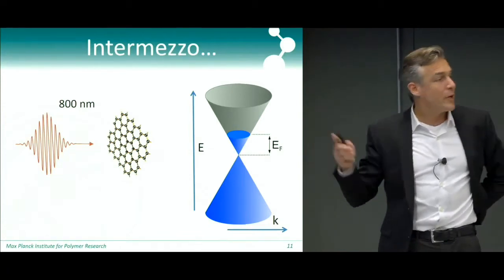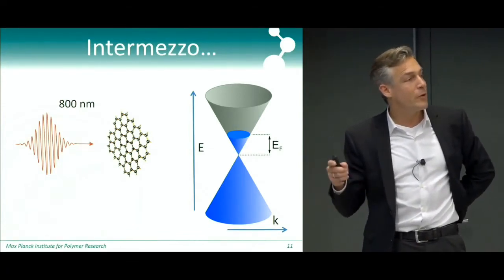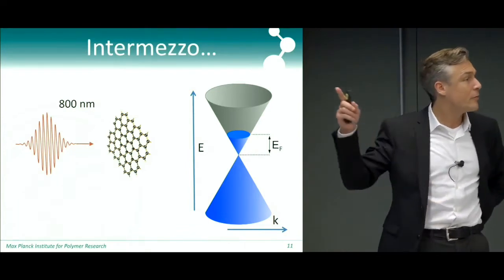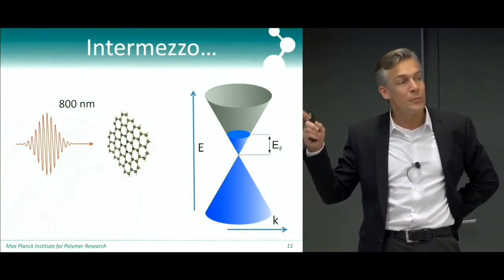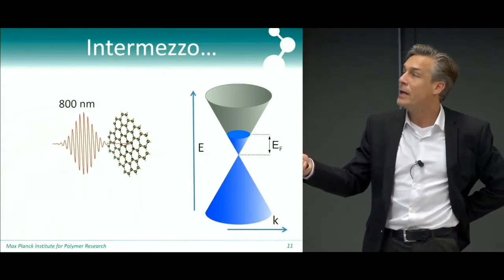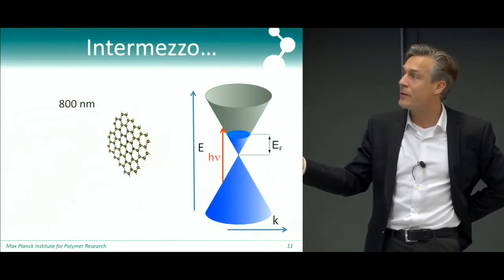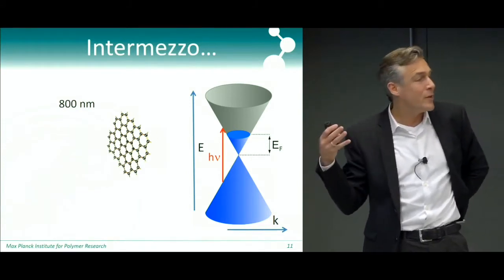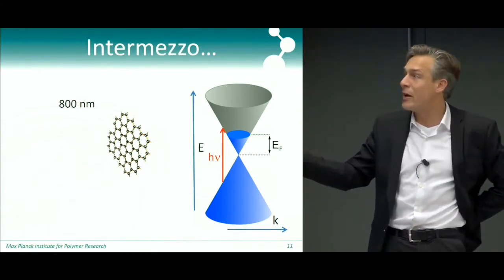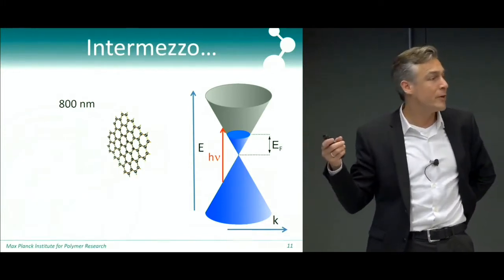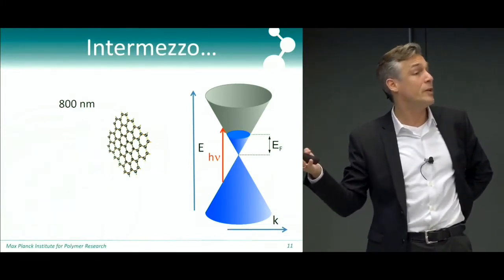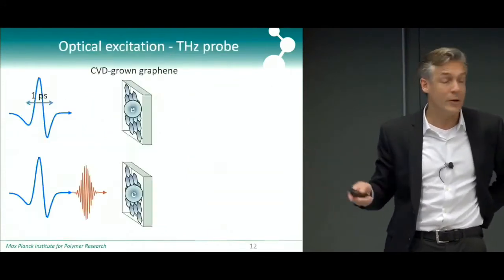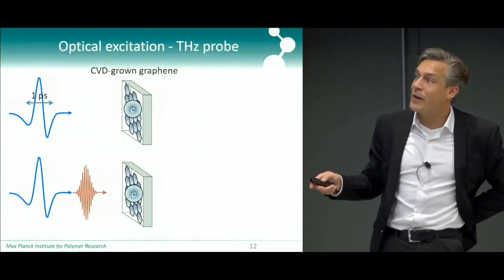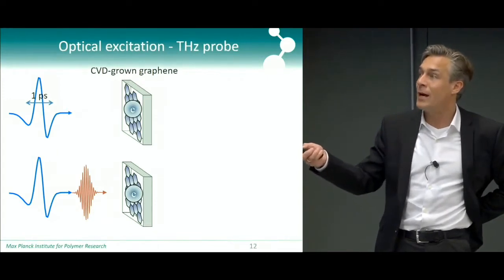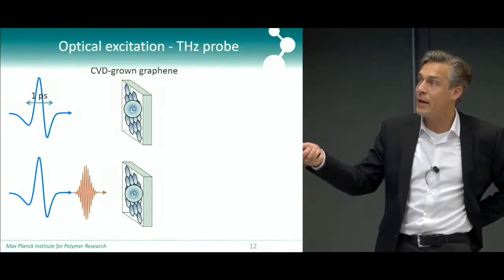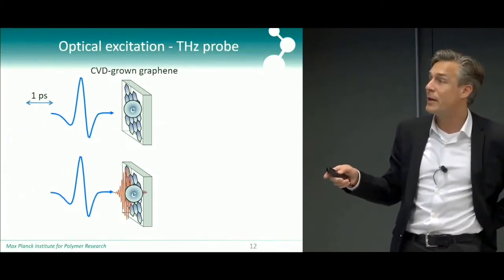So when we started investigating graphene, we actually wanted to measure the photoconductivity. So now I've shown you how we can measure the steady state conductivity, but we were interested in measuring the photoconductivity. And so we photoexcited the graphene. And the idea that we had initially was quite naive, that we will generate additional free carriers, and that should increase the conductivity of the graphene, like with any semiconductor. Now, we were very surprised when we did this experiment, comparing the photoexcited case with the non-photoexcited case, and again,